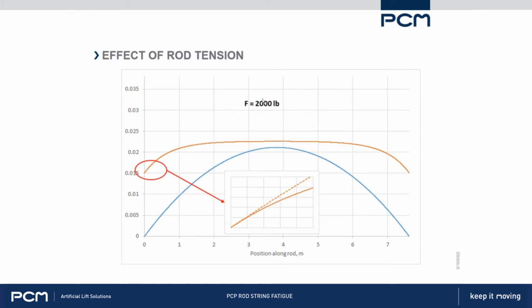The orange line represents the surface of the rod. It's offset at each end by the size of the coupling. So a full-size coupling on a 1-inch rod will offset the rod by about 15 millimeters from the tubing wall. So that's what we have here. At each end where the couplings are, it's parallel to the tubing wall, and it stays parallel. It doesn't matter what happens, it's staying parallel.